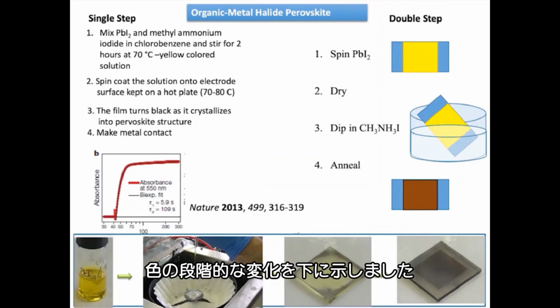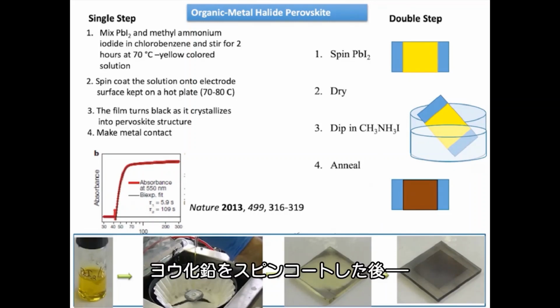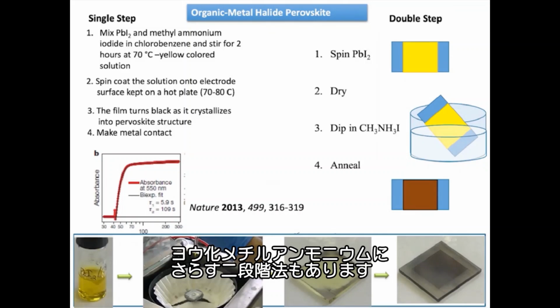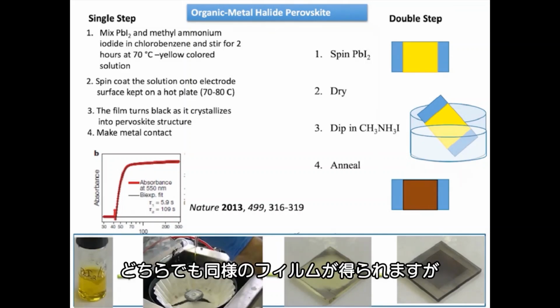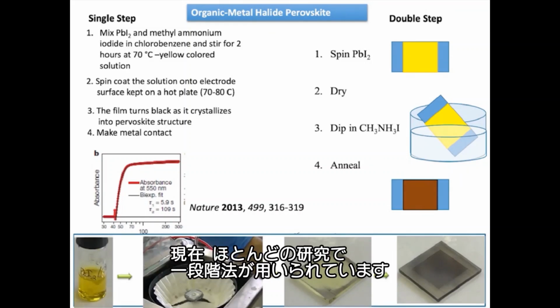You can also use a two-step method where you first spin coat lead iodide and then expose it to methyl ammonium iodide. So both give the same type of films, but most of the studies today work with this single step method.